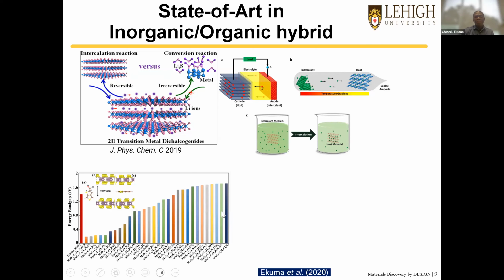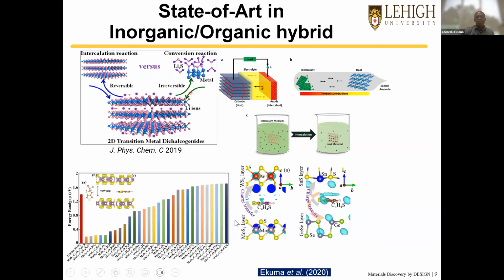This is a snapshot of some of our high throughput screening where we can systematically tune the electronic band gap of MoS2 using various conjugated molecules. Again, these are small conjugated molecules of the order of 30 atoms per molecule. And this is also a snapshot where we put something like thiophene between two, this is MoS2 and this is tungsten disulfide. And this is SnS. So this is like the transition metal dichalcogenide, and these are like the transition metal monochalcogenide, something like GeS, SnS, and the rest of them.